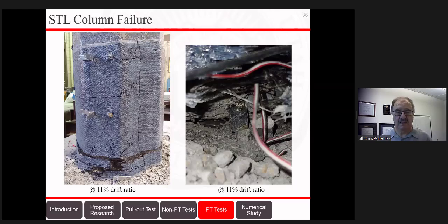The steel column had a similar fate. We saw the first crack in the carbon fiber at around 3%. At 9%, we saw a fracture, that you can see here on this wrap, which means it worked very well. Again, a couple of inches from the bottom. And you can see on the right that a steel bar actually fractured at around 11% drift ratio on one side of the column, on the west side. And then on the east side, we saw a rupture at 12% drift ratio. So this is a very good performance.